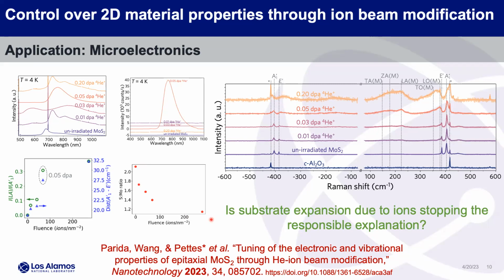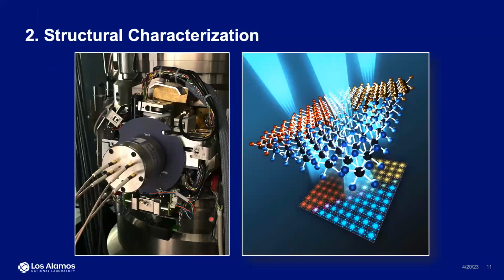But you can see how useful this can be as opposed to just putting it in the FIB and hitting it with ions. So the next step, I'm going to show you this pretty quickly because I want to get to the synth portion. The next step is we're doing structural characterization with electron microscopy. So now this transitions to diffraction analysis mainly. And so what we do is we have an in situ heating holder. We have a bunch of in situ holders, but me personally, I have in situ MEMS-based heating holders. And we hit our materials.